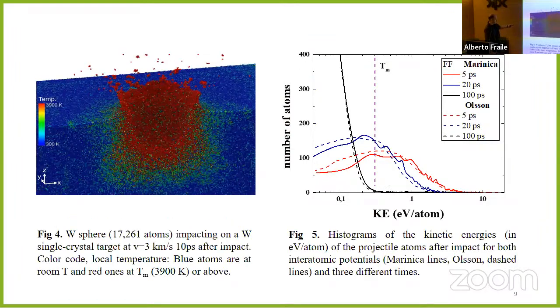Then we can do the simulations, and we can see, for example, here, this is the impact. The color code is the kinetic energy of the atoms. So what we can see is how the kinetic energy of the atoms of the projectile are at very high kinetic energies at short times, and then this histogram moves to the left, meaning that they stop in these 100 picoseconds, they are all at low kinetic energy below melting point. And with the two potentials, these kind of histograms are similar. So it would mean that the thermal conductivity more or less is the same in both, with both potentials.